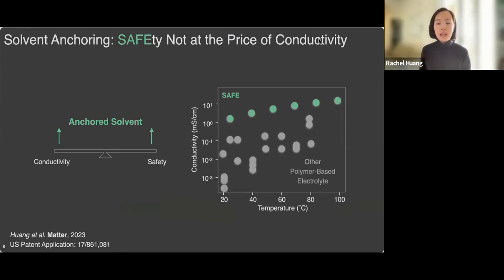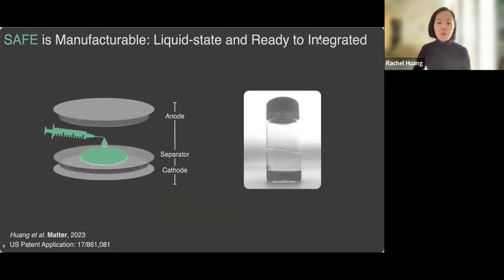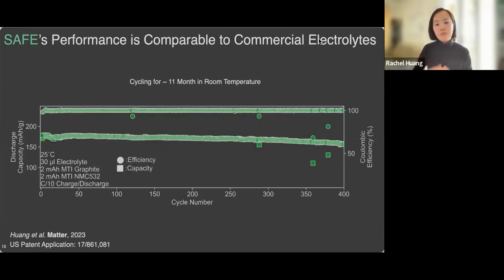Our SAFE electrolyte has elevated conductivities compared to other existing polymer-based electrolytes over a wide temperature range. Other than conductivity, SAFE electrolyte is actually a liquid state, which is different from ceramic solid-state electrolytes. It can be readily used with existing battery electrodes and battery stack geometries without additional modifications, which makes it quite manufacturable. SAFE electrolytes can also be readily integrated into batteries and show stable long-term cycling performance. They're just a replacement for commercially available electrolytes, but safer.